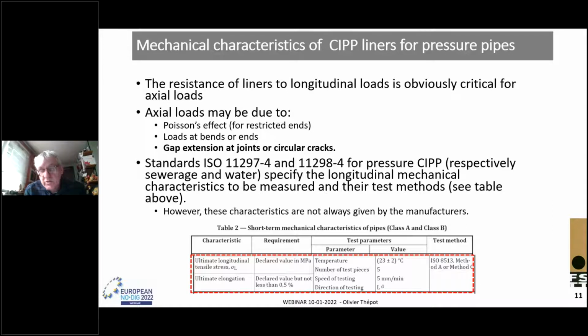Axial loads may be due to Poisson effect for restrained ends, loads at bends or ends, gap extension at joints or circular cracks. This loading is much less known than the other two. It is an imposed displacement and not an imposed force, which is very different. Standards ISO 11297-4 and 11298-4 for pressure CIPP, respectively sewage and water, specify the longitudinal mechanical characteristics to be measured and their test method, which are the ultimate longitudinal tensile stress and the ultimate elongation.